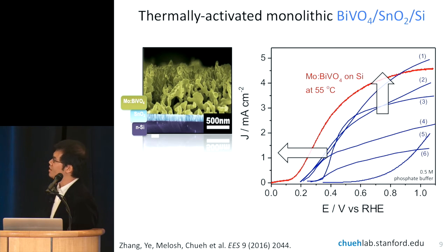So by adding a silicon solar cell embedded in our photoelectrochemical electrode, we're able to push the voltage further to the left, which is what you desire. We're able to add about 300 millivolt additional into the system, and by comparing against other types of bismuth vanadate-based cells, we're able to achieve a very low onset potential and also a very high current density, and this is by combining both managing the voltage and also enhancing the current with temperature.